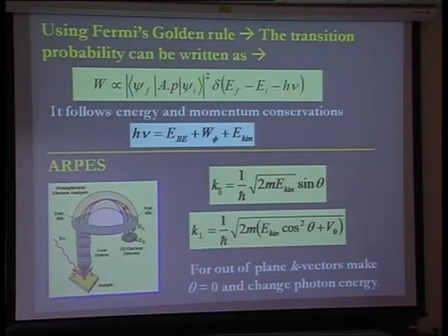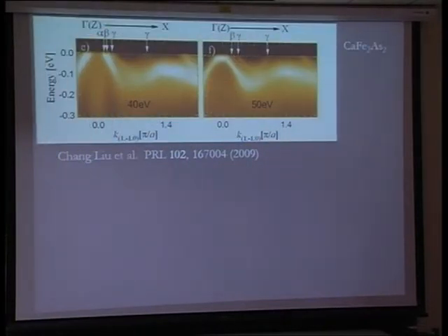So at normal emission geometry, you change the photon energy, that means you change the kinetic energy, and you can map the kz vector. So if you change the photon energy, you are mapping kz, and of course at a particular energy you can change the angle and you get these two vectors to map the Fermi surface and the band structure of any material. So this calcium iron arsenide 122 has been studied, as I said, extensively.